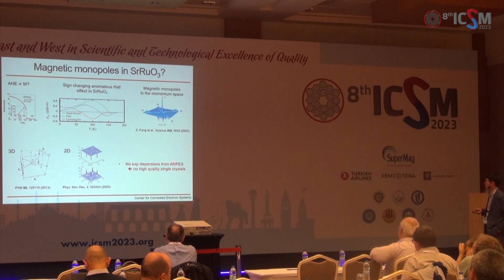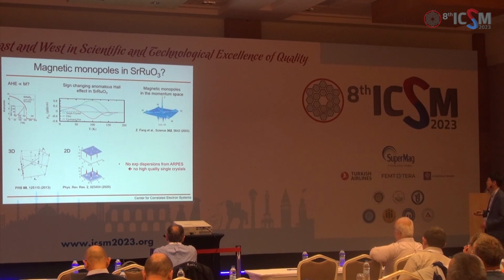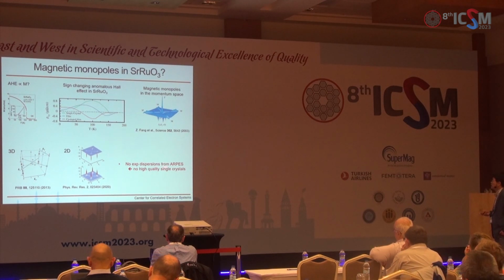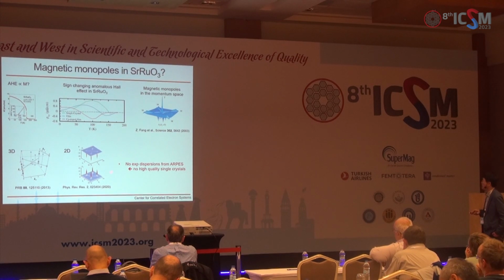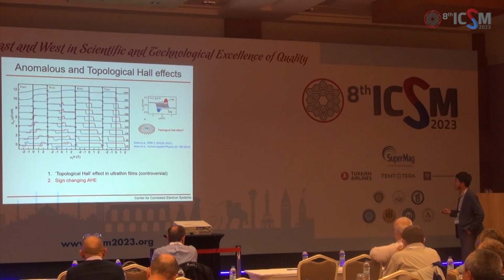One problem in this business was that there's no experimental ARPES data on strontium ruthenate, and that's because there was no suitable single crystal. So one possibility is that, of course, we can now grow high quality thin films that can be considered as single crystals. So we can do ARPES on these films and see where these Berry curvature sources are. So that was the idea.